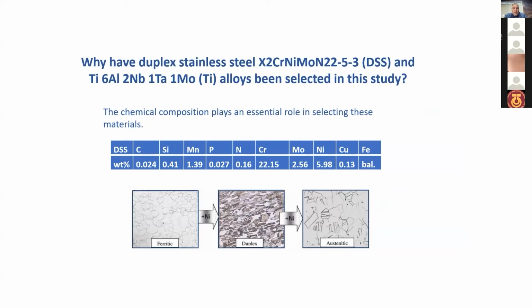Now, why have the duplex stainless steel and the titanium alloys been selected in this study? We selected the duplex stainless steel as the superior alloy in the stainless steel group regarding corrosion resistance. Previous studies indicate that duplex steel is superior to the other types of stainless steel regarding corrosion resistance, because it has elements that contribute to the stability of the oxide film.